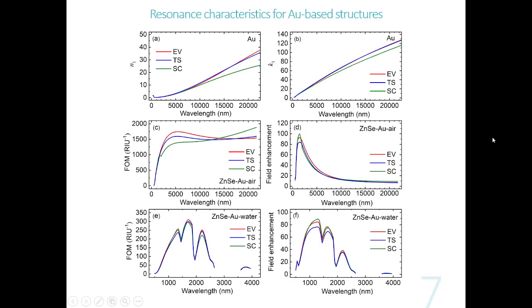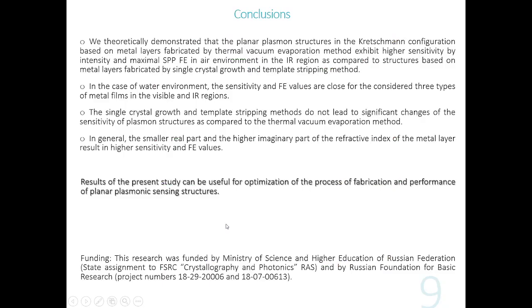If we go to the gold-based structure, it would be hard to notice some differences. It is due to the almost similar values of the refractive index of the films fabricated using the three techniques. So it leads to quite the same values of the sensitivity and the field enhancement in the entire considered region for air and for water.